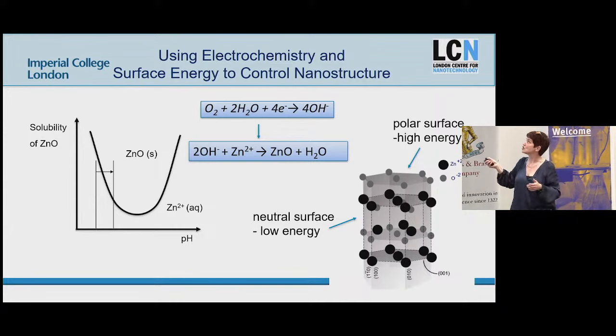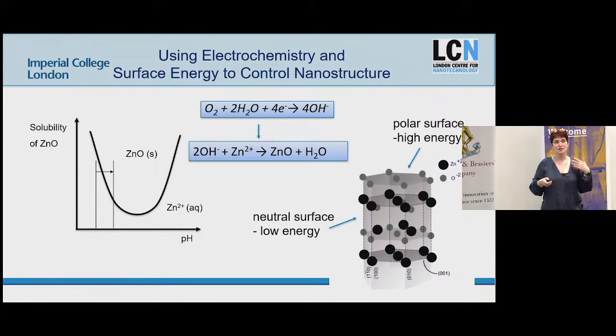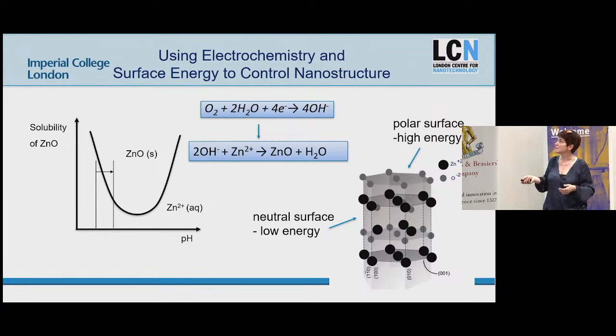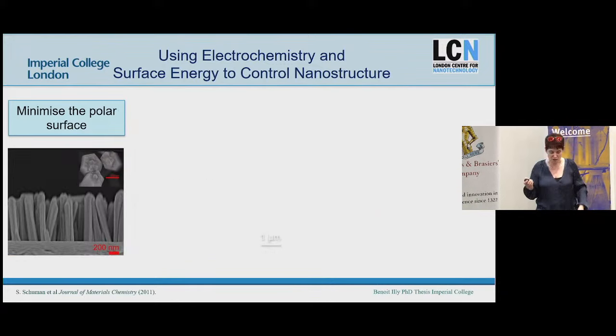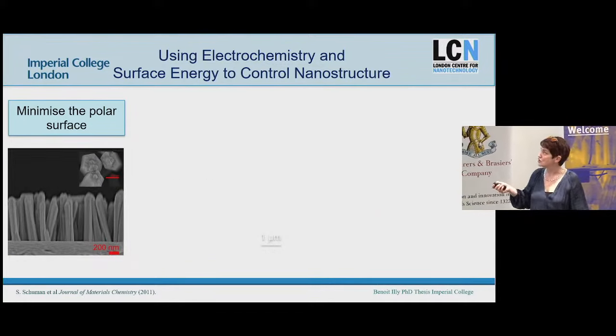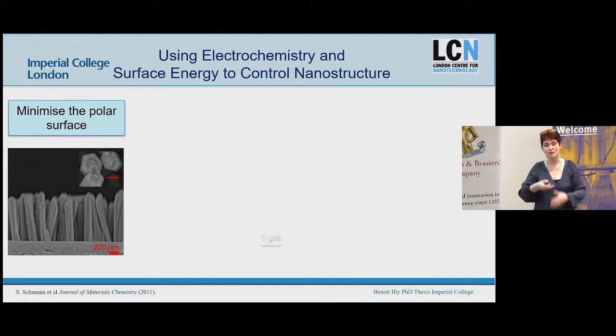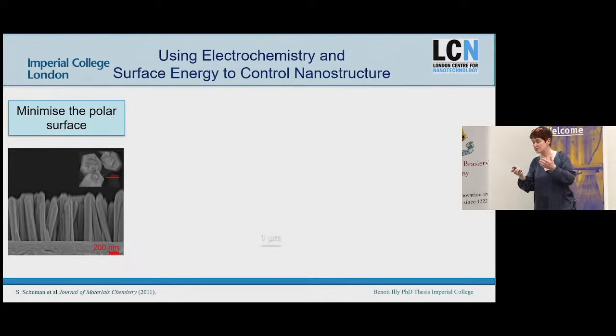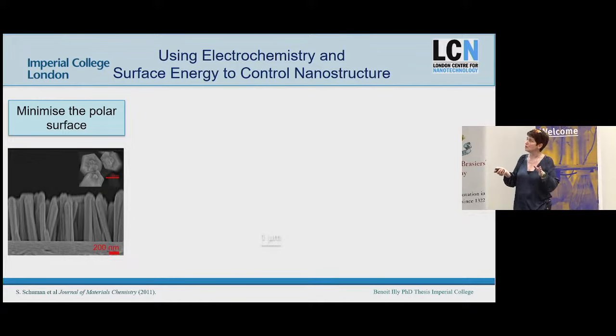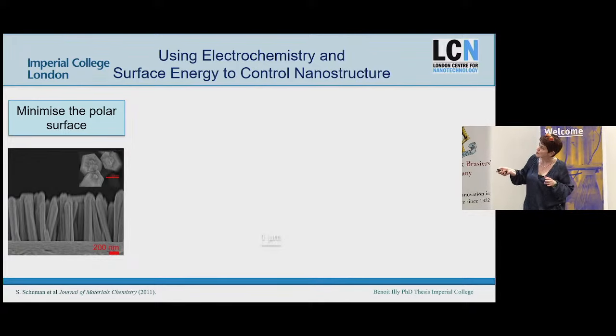And you can use that change in surface energy to get structures that you want or might be desirable. So here's what you can do. You can play with that surface energy feature. So you can minimize the polar surface by growing the samples in a very controlled electrochemical way. And what you can do is get it to grow, basically, as rods, nano rods.